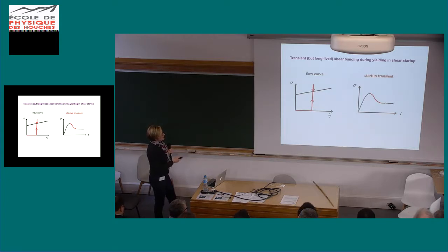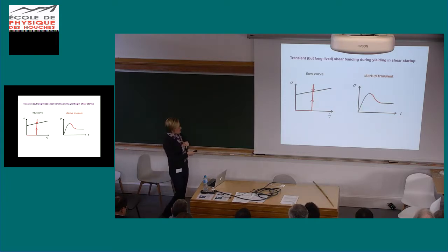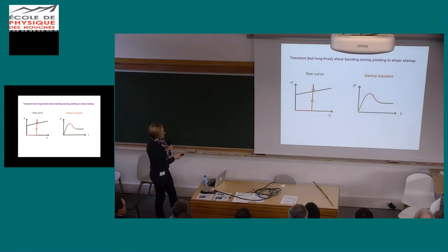Now, in the limit of long times, that has to settle to the steady state flow curve value. At short times, however, the stress increases linearly with time, and so with accumulating strain. So that's elastic solid-like behavior. And then there's typically an overshoot, and then as one comes off the overshoot, there's a region of decreasing stress as a function of time.